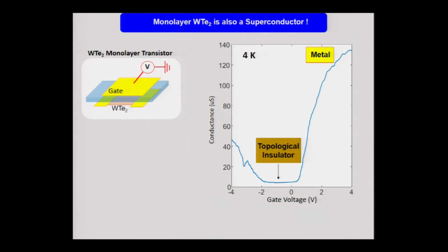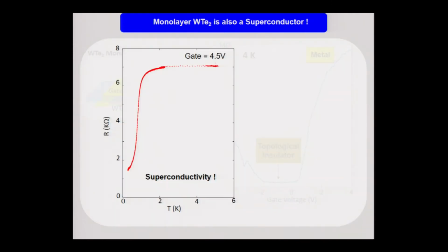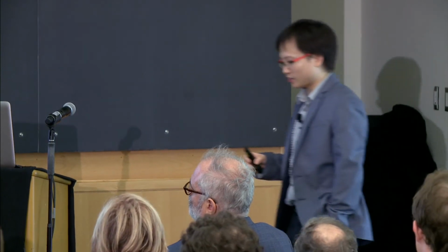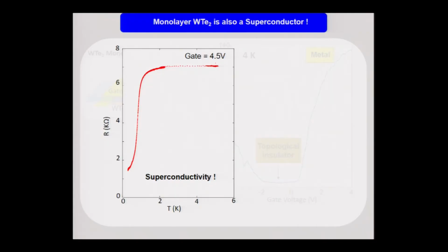What's interesting here, if I focus on the metallic state, park the gate voltage here, and monitor the resistance of the flake as a function of temperature, I see this. The resistance stays constant when I decrease the temperature, and suddenly it drops to a very low value at around 1 Kelvin. So this is a behavior that looks like superconductivity. Now experimentalists can also have a standard check to say whether this is a superconducting transition or not. And the answer is also yes. We did a series of checks, but I'm not going to show the details, only to tell you that this is indeed a superconducting transition.